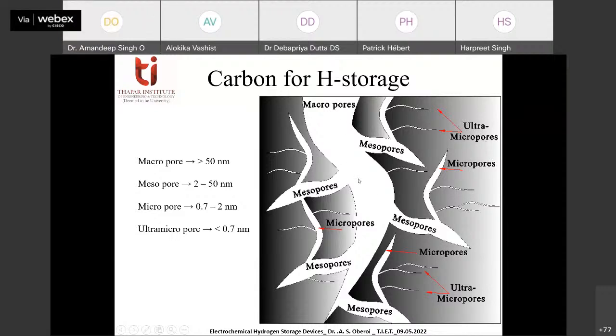And all the rest of these pores play a significant role in the transportation of the hydrogen molecules inside these deepest pores. At the micropores, these inside surfaces are available for hydrogen molecules to form a chemical bond with the host material. Okay, and these chemical bonds are not very strong. When we start extracting or drawing out the current, under the potential difference which is created, these bonds break, and the stored hydrogen moves out of the storage, and then it is ready to react with the oxygen to give you the electricity as well as the water.